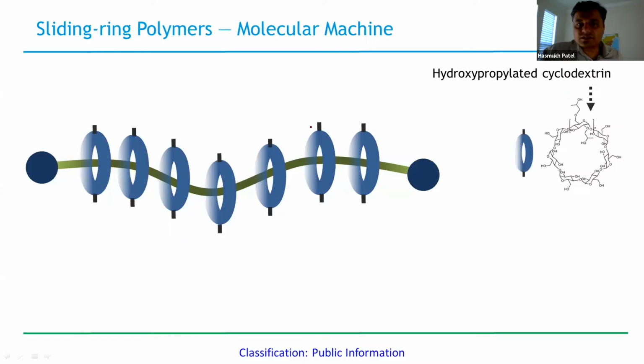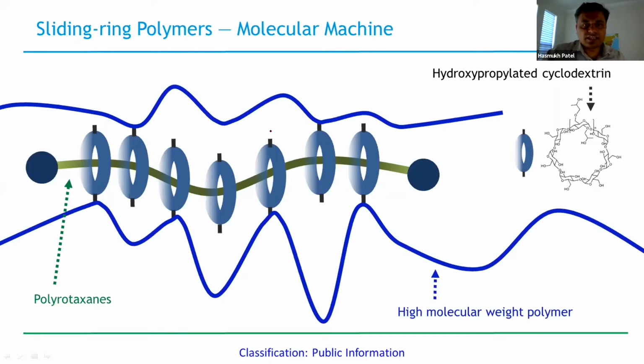So what we did was functionalize some of the hydroxyl groups with hydroxypropylated functionalities. As you can see here, we changed some of the hydroxyl groups with hydroxypropyl functionality. And once we have this functionality, we linked these polyrotaxane molecules with high molecular weight polymers. Here we use polyacrylic acid, so that this polyrotaxane is blended within the polyacrylic acid. As you can see in these structures, if you imagine pulling these polymers from the top and the bottom, what will we see? We see the motion or sliding of the cyclic molecules onto the linear chain, and you can have a maximum strain with minimum stress, and it can also distribute the stresses within the polymeric matrix.